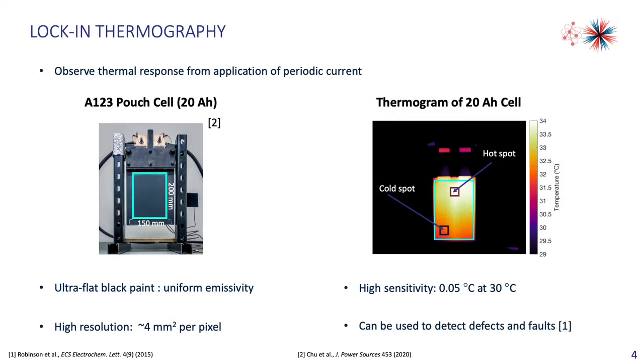An experimental setup was designed and created as shown. The rig was designed to do lock-in thermography, but the battery is hung vertically to avoid insulating the two largest faces where heat can be dissipated. The surface is painted matte black to aid with reflections and gives off a uniform emissivity.